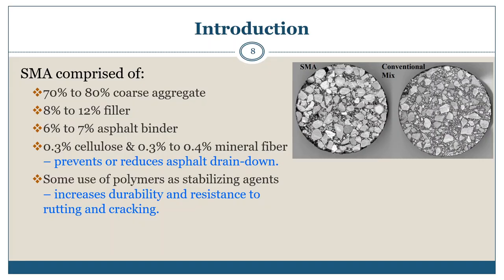SMA mixtures are comprised of 70 to 80% coarse aggregate, 8% to 12% filler, 6 to 7% asphalt binder, 0.3% cellulose, and 0.3 to 0.4% mineral fiber. The cellulose and mineral fiber prevent or reduce asphalt drain down. The higher asphalt content compared to conventional dense graded mixes increases the compliance of the mixture, reducing the probability for thermal cracking, and also increases the resistance to fatigue cracking. Some use of polymers as stabilizing agents are also included in SMA mixtures, which also increases durability and increases the resistance to cracking and rutting.